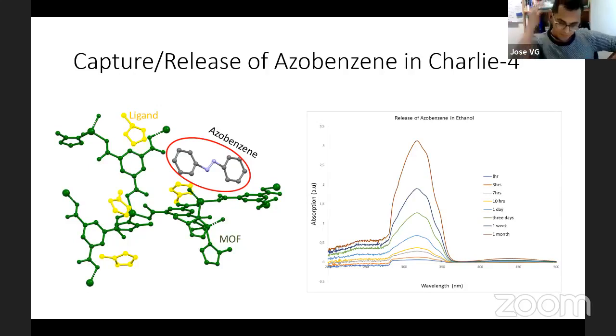We normally use UV spectra, tracking over time how much the azobenzene is being released in the alcohol. And as you see, it's a very slow release. It's not a sudden release that's usually observed, for example, in other MOFs whose channels or pores are not blockaded, where the release is usually sudden. Here the release is very slow, very gradual, which can give another application for other types of reactions.